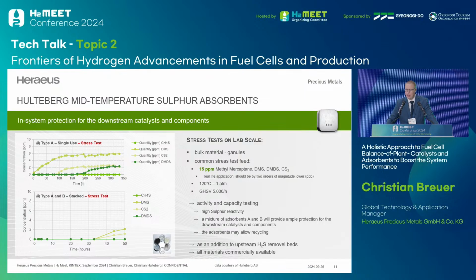will help to catch also other trace components, which, as I said, given our long durability targets, will also accumulate in the system over time, and they are designed to operate at moderate temperatures. Here we did a stress test showing that by a combination of different getter materials, we get, as shown in the lower graph, a very nice time of protection.